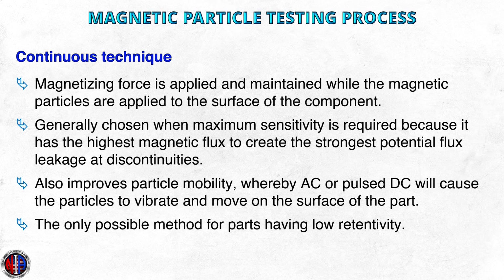AC or pulse DC will cause the particles to vibrate and move on the surface of the part. This movement allows the particles to travel to leakage sites and create a more visible indication. Overutilization of the continuous technique may create excessive heating in the part, so headshots must be used in moderation. The continuous technique is the only possible method for parts having low retentivity.